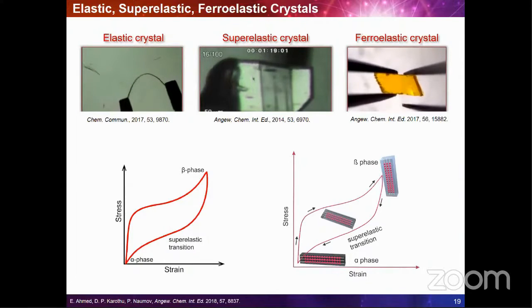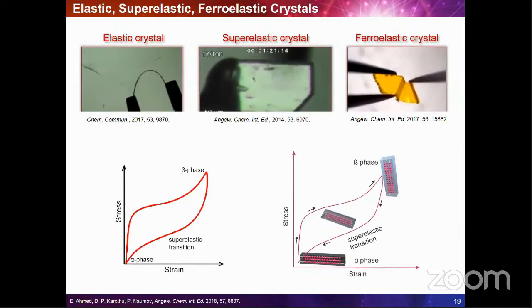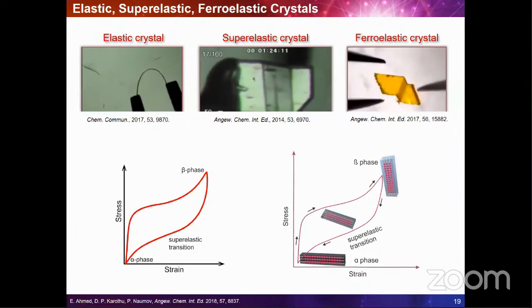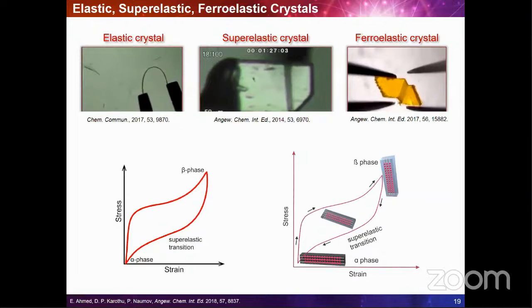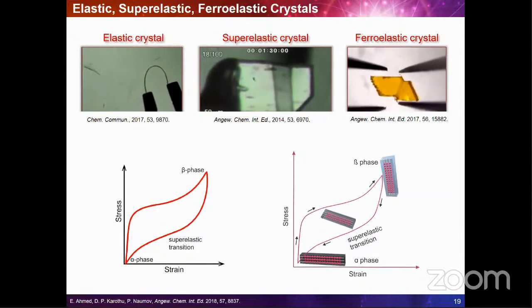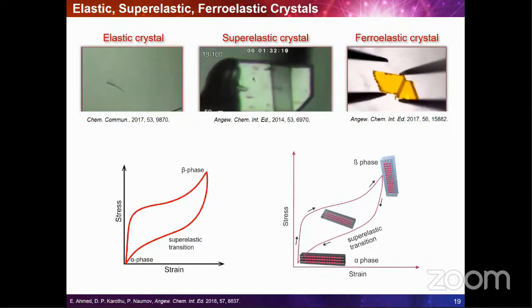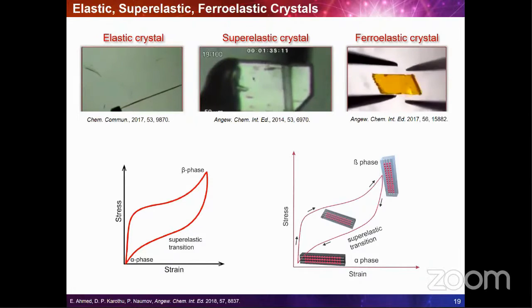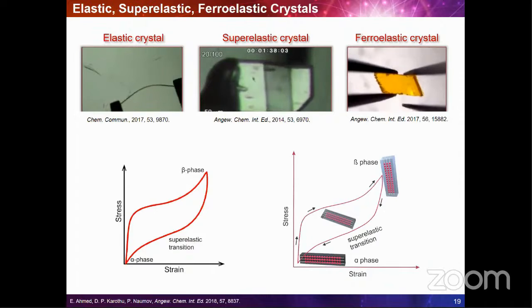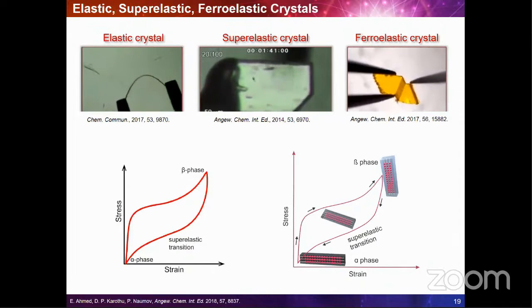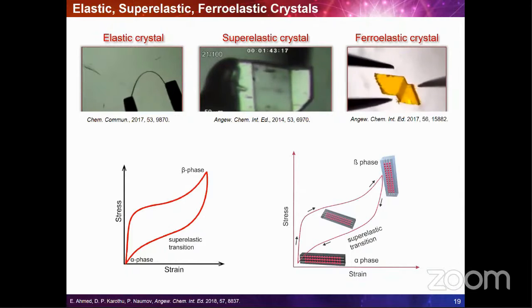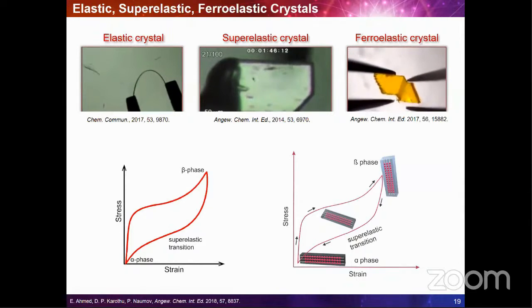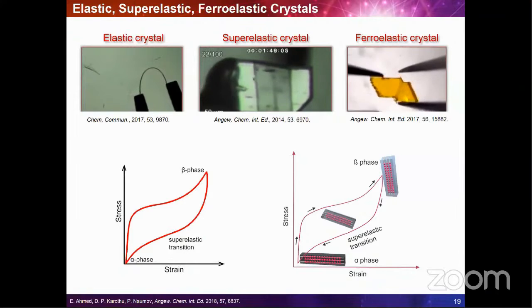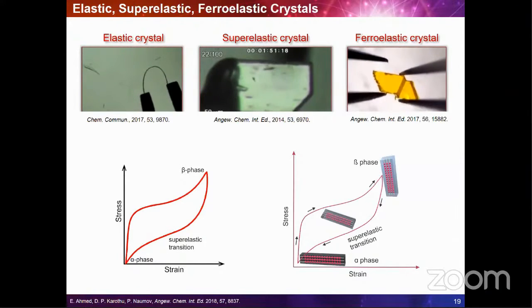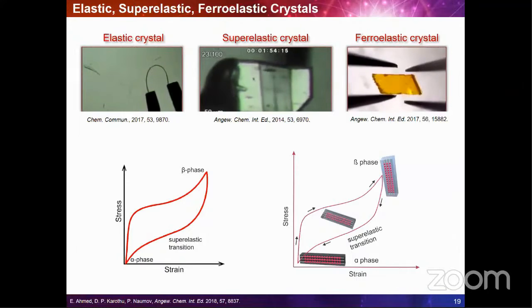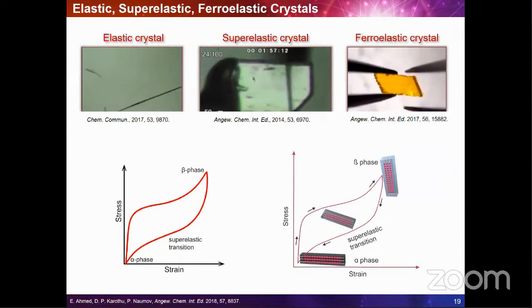Now, here on the right-hand side, you can also see ferroelastic crystals. In contrast to superelasticity, where the stress-induced deformation can be recovered by removal of the stress or by heating to the temperature of the reverse transformation, in ferroelasticity the stress-induced deformation is irreversible. It is associated with a reorientation process where the deformation, which can be twin or polymorphic, can be reversed by applying a reverse stress to these materials. So there's a lot of excitement and also studies into these materials and comparison of these properties.